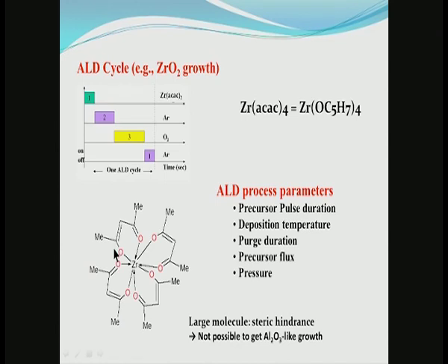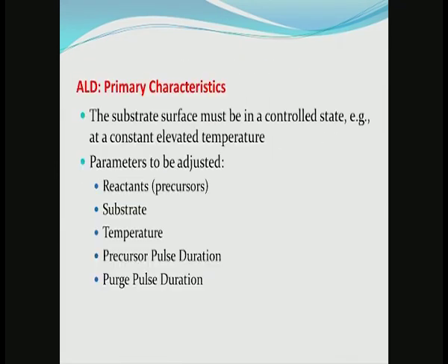So, when they are gone, what you are left with is a much smaller area that is covered by the desired zirconium oxide species, and therefore, when the next molecule comes here, there is a significant amount of void between this ZrO2 entity and the neighboring ZrO2 entity after the reaction takes place. Therefore, the coverage is much less than 1 monolayer after 1 cycle, and therefore, this is called steric hindrance of the process.